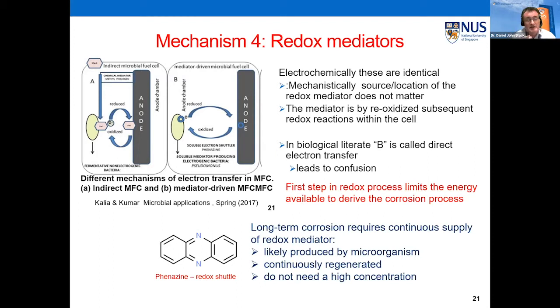And it's important because if you think of energy terms, there's plenty of energy when you reduce sulfate to corrode the metal. But the energy available for the corrosion is actually the first step in the redox process. So this step to the redox mediator on the surface, that's all the energy you have for the corrosion. You don't have the entire energy from sulfate reduction available. So it does make quite a difference when you're trying to model what's happening. It's also to say that these redox mediators don't need to be in high concentrations because they're going to be continuously regenerated.